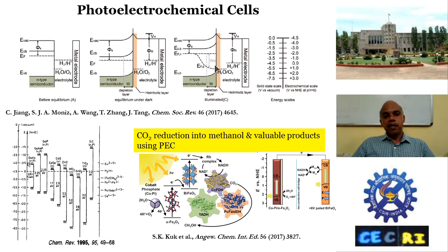Various semiconductors have been looked at, like gallium arsenide, gallium phosphide, cadmium sulfide, zinc oxide, depending on their conduction band level or Fermi level with reference to the hydrogen reduction potential. Some of them can be better materials, and do not even require any applied bias to split the water into hydrogen. However, their stability is an issue, since most of them undergo a photocorrosion process and dissolve. For example, in cadmium sulfide, the cadmium ions dissolve into the solution. There are other ways to protect against this photocorrosion, by having a core-shell structure of the semiconductors, so that you can improve the properties or stability of these semiconductors for their application.